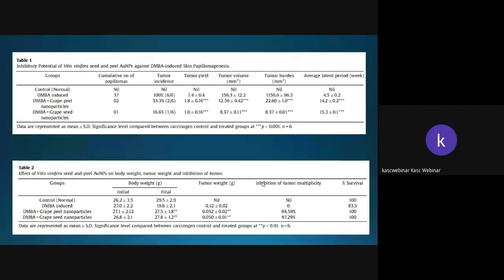So we have seen the cumulative number of papillomas. We have the control, DMBA induced, DMBA with grape peel nanoparticles, and DMBA with grape seed nanoparticles. DMBA is the agent which can cause cancer. In the DMBA group there were 37 papillomas identified in the animals, and we compared this with the peel nanoparticles and seed nanoparticles. Comparatively, the grape seed has higher activity against cancer than the grape peel. Here you can see tumor incidence, tumor yield, tumor volume, tumor burden, and average latent period, all of which prove that the gold nanoparticles are a very good anti-cancer agent.